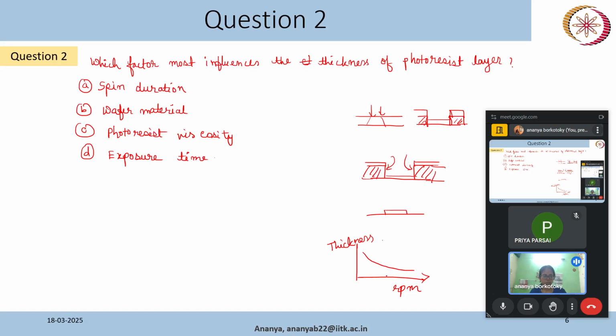So we start with some desired thickness, set our spin coater to the corresponding speed, and do the spin coating. After that we measure the thickness and verify that we are actually getting it. Remember, I mentioned that over time there may be some particle formation and our photoresist may degrade, so you may not get the exact thickness as per the data sheet. So that has to be calibrated: we should check and optimize our process properly, to see what thickness we are getting at whatever speed we set.